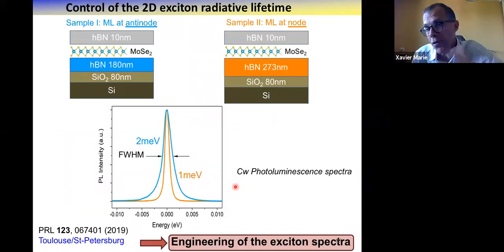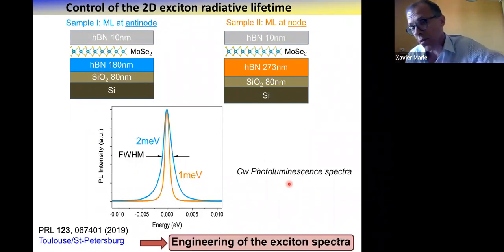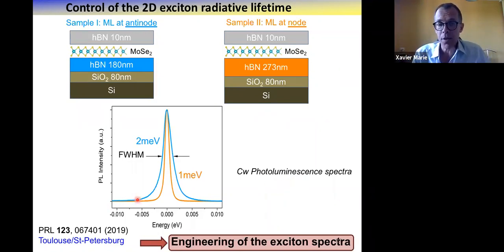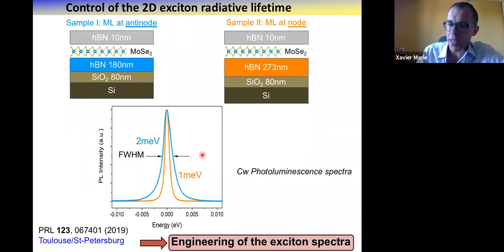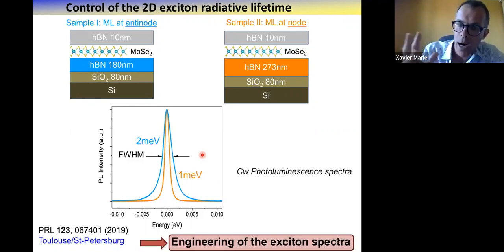And in fact, if you want to show this effect, you don't need heavy time-resolved equipment. You just need a good sample. And here I compare the two samples designed to be either at the antinode or at the node of the optical field intensity. So this is the same structure. You just change the bottom hBN thickness and you measure the photoluminescence spectra in CW conditions. And you indeed find that the line width of the sample at the antinode, with fast recombination, is large, 2 meV, compared to the situation where you are at the node. So indeed, the line is not fully controlled by radiative recombination, but radiative recombination is a key ingredient. We are close to the homogeneous broadening of the line. And with this, you can engineer the exciton spectra by the control of the environment.